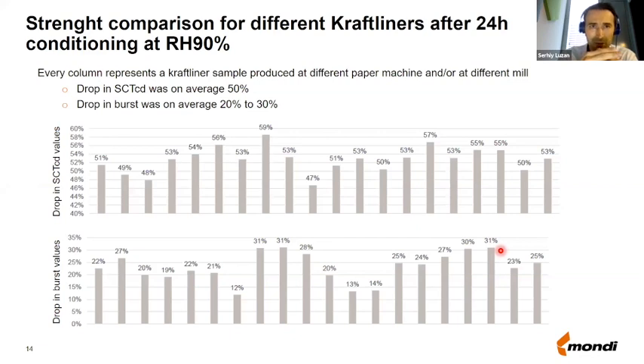If you remember, I was mentioning on one of the previous slides that when paper absorbs water, it becomes more flexible, more stretching. And the burst is a combination of the resistance of paper to stretching. So basically, if the paper becomes weaker but more stretchable, then the burst is dropping not to the same extent as SCT. But my key message here is that the test of conditioning paper at high humidity and testing afterwards may show you some difference, but the differences between different papers would not be so drastic. The drop in the performance would be quite similar, about 50% for the SCT and about 20 to 30% for burst.